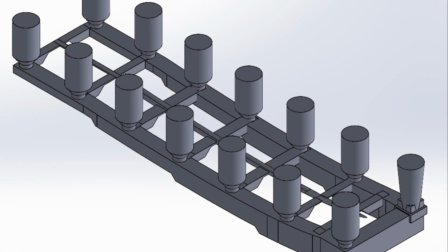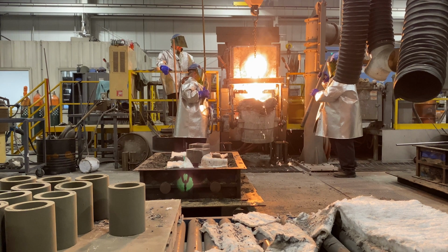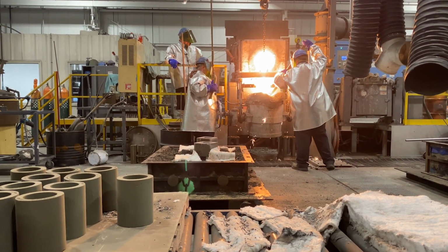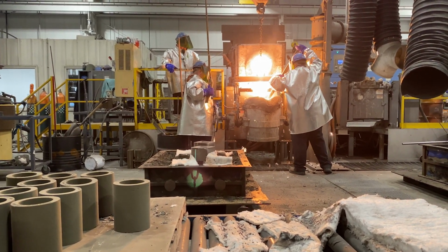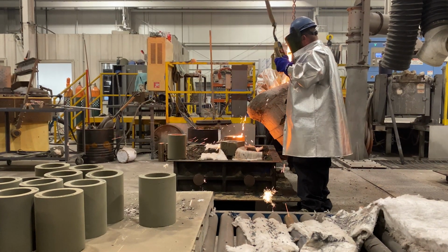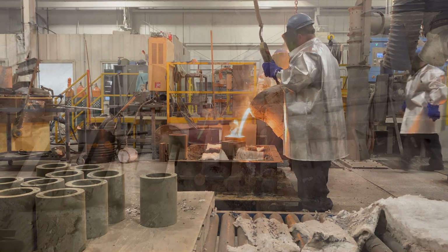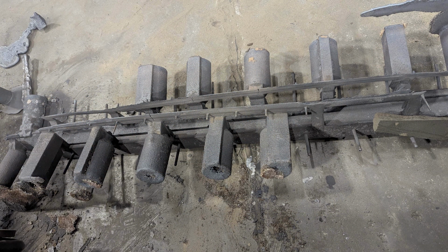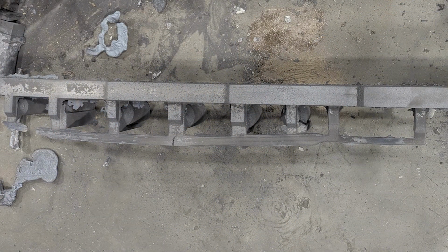This version was created in collaboration with our industry partner, Kimura Foundry. It included many risers very close to the blade profile so that they would fill the profile during shrinkage and help with porosity. After many weeks of attempting to cast successfully, we decided that due to time constraints and casting failures, we would not continue with this project, but it gave us valuable experience in creating a model, creating copes and drags, and collaborating with industry partners.